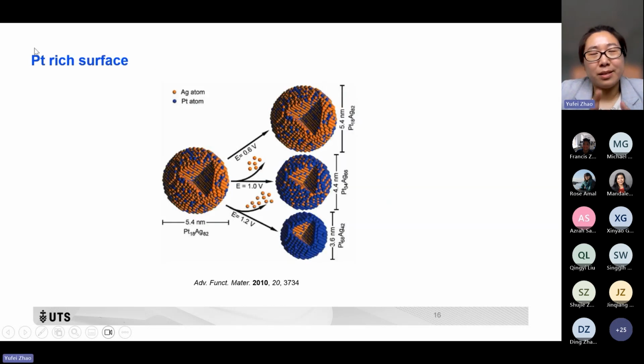Besides working on the single atoms and the atomic clusters, we have also done a few works on alloys. For the Pt-based alloys, we normally incorporate non-precious metals like transition metals into these Pt structures to lower the cost and also modify the electronic structure of the platinum. Like in this picture, we try to use different methods to expose more Pt on the surface. Because for electrocatalysis, we know the reactants need to interact with the active site to accelerate this process. So if we expose more platinum on the surface of these materials, all the exposed platinum can act as the active site for the HER process.